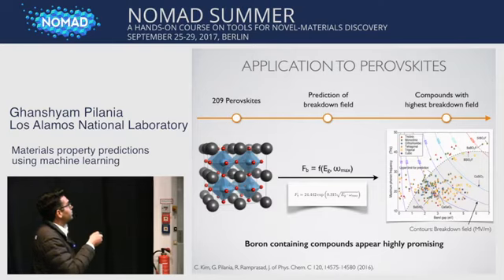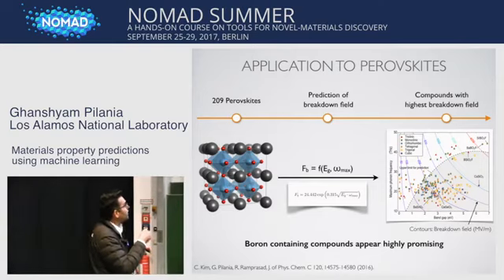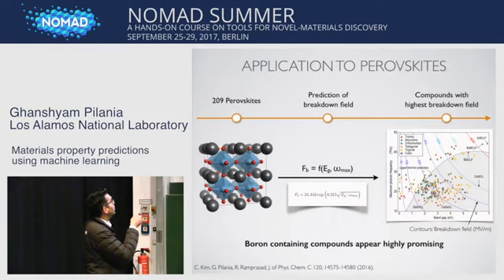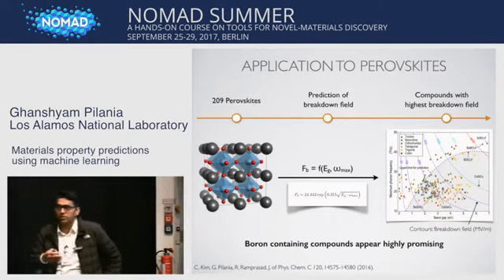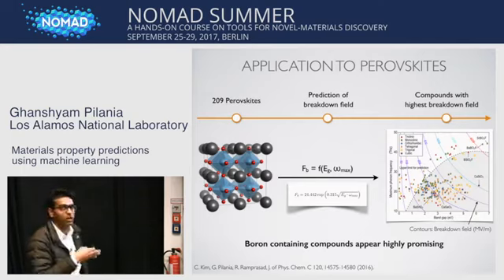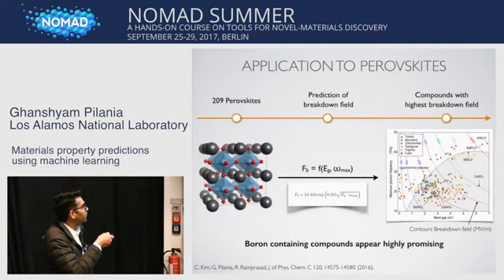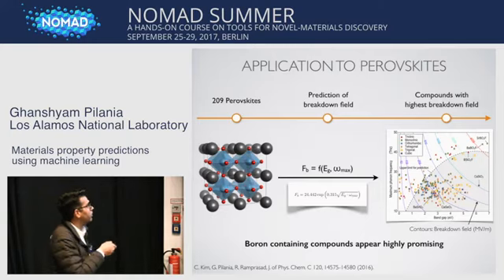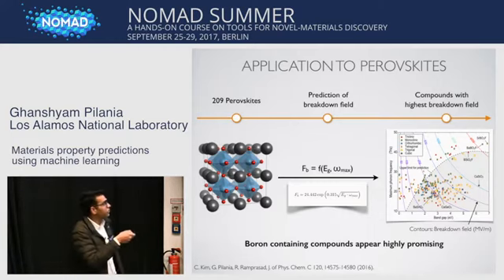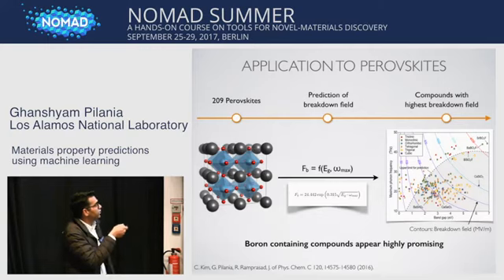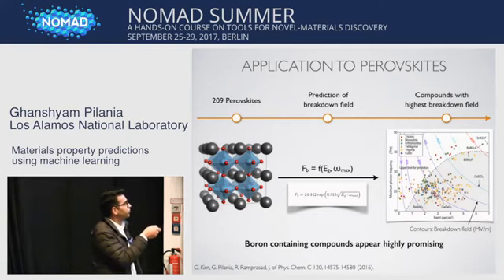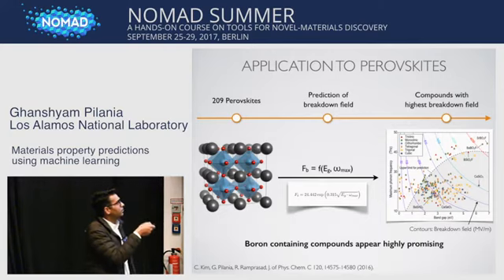So there are several thousand perovskites, ABX3 type of compounds, and we identify which one of these are stable in perovskite structure, and we look for insulating compounds, so have finite band gap, and there are about 200 of these. And then we use this machine learning identified form to predict the breakdown field strength using the band gap and phonon cutoff frequency on this set. So the results are shown here. On the x-axis and y-axis are our two features, band gap and phonon cutoff frequency, and the contours are the breakdown field strength.